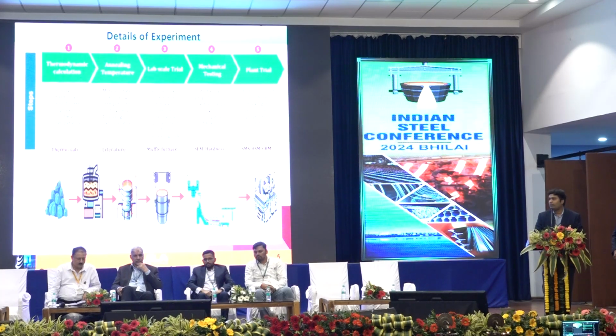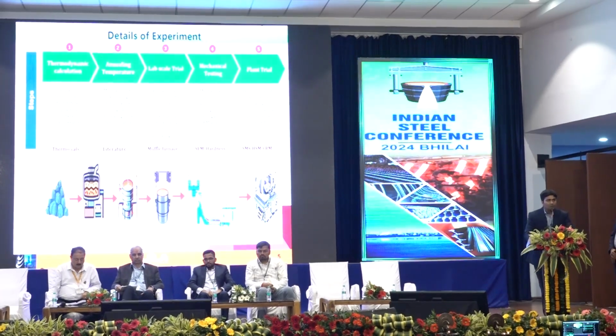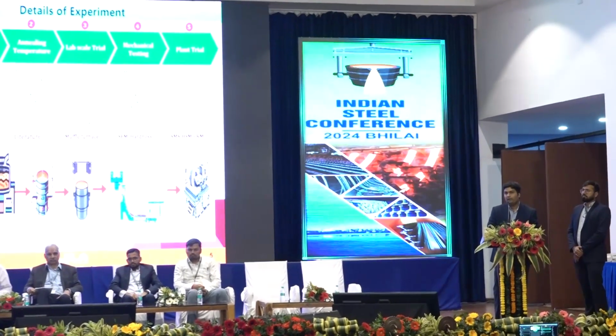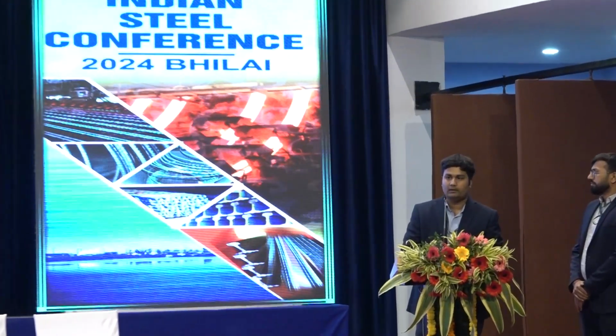So first up, for development, we used Thermo-Calc. Using Thermo-Calc, we find out what the phase fractions are, what liquid phases are present at what temperature. After that, the bell annealing cycle was designed, at what temperature annealing is required. After that, the lab scale trial was done. Further, the plant scale trial was done and the material was dispatched for the customer application. We are primarily through the scrap route. So we have electric arc furnaces, AOD, continuous caster, roughing mill and reheating furnaces.